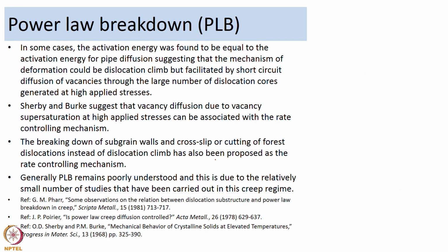So, pipe diffusion, the mechanism of, so basically what happens in pipe diffusion is you have a short circuit diffusion of vacancies through the large number of dislocation cores generated by the high applied stress. So, you have short circuit diffusion of vacancies through a large number of dislocation cores.